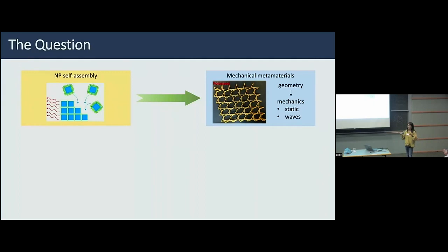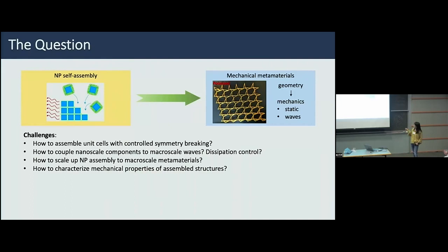However, as we've spent more time trying to establish such a connection, we now understand there are actually a lot of challenges — this is a very interesting physics question. If you want an interesting mechanical metamaterial with special properties, most of the time you cannot do it with a close-packed structure. You need the structure to be open, sometimes flexible, and you need to break symmetries such as inversion symmetry or time reversal symmetry, which are all challenging to achieve with nanoparticle assembly.